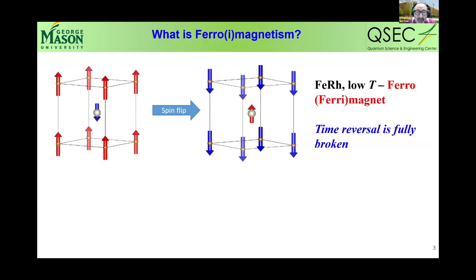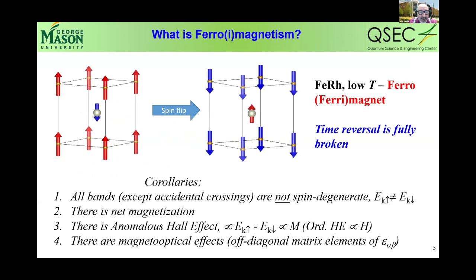So to begin with, what is ferromagnetism? Ferromagnetism from the symmetry point of view is a material where time reversal, which is equivalent to spin flip, leads to a crystal which is symmetrically different. There's no symmetry operation which can map the left panel onto the right panel. Now, because these two things are different, that means that the band structure in two spin channels is generically different, like in two different materials. So the bands are not spin degenerate.